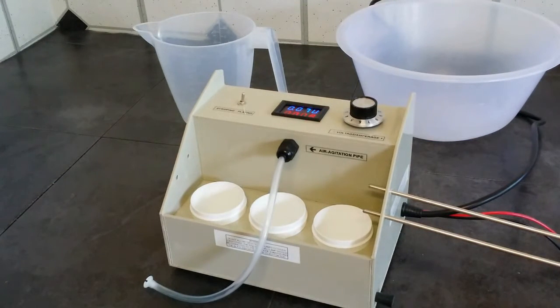Please remember to wait for about 5 to 10 minutes to ensure your solutions in the tanks warm up to about 50 to 60 degrees Celsius. This will speed up the reactions in the tank.